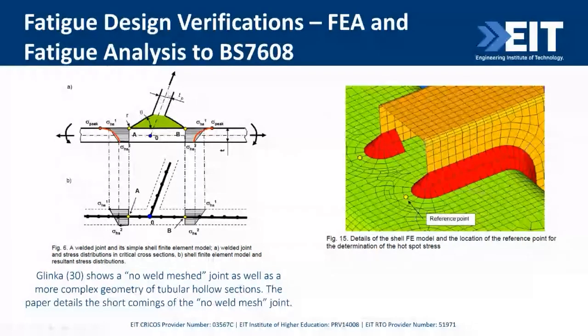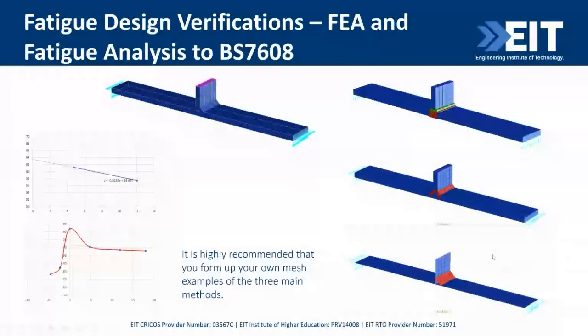So obviously you've got a mid-plane shell element for this element here, and also on the horizontal plate, mid-plane, give the shell element thickness, and then you need to have an insert weld element as well, or else increase thickness, because that no weld simulation is not good enough to look at hollow tubular section joints or more complex joints than a simple laboratory joint. You can do this yourself, like I've done. Set up a solid mesh with the gap in there, as you see, or your added thickness mesh, or your insert